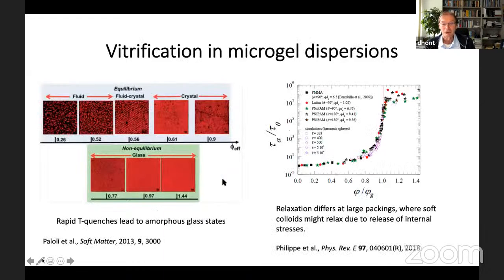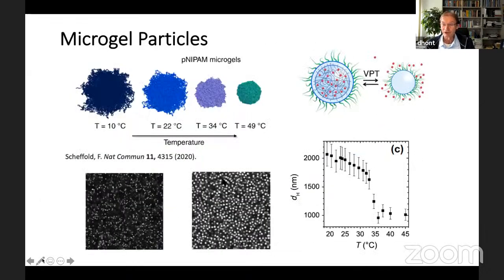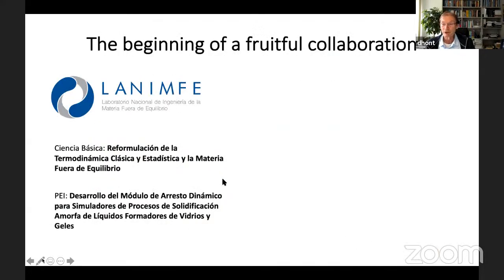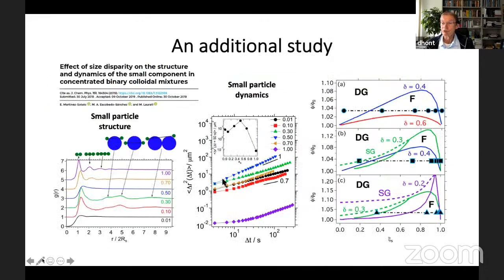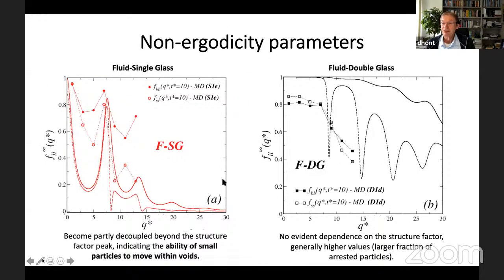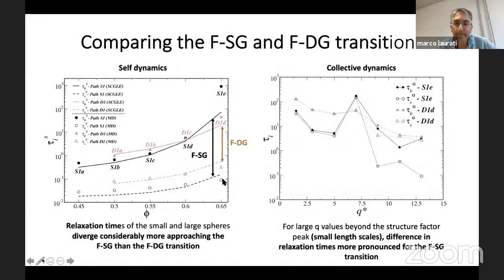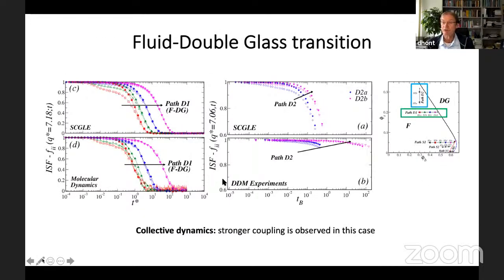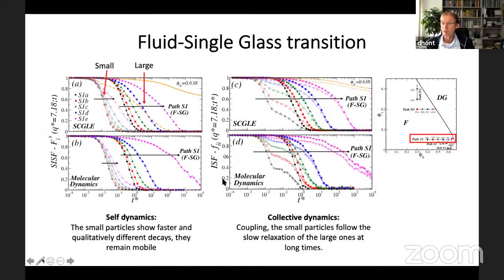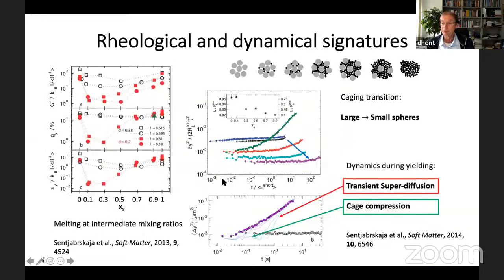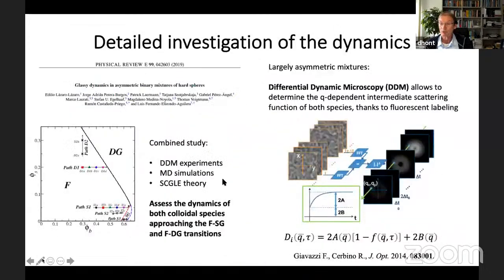But now you find a single glass up to a size ratio of 0.4, where the small ones cannot move through the holes between the big ones. So I don't understand in that case how you can have a single glass. There should be a large fraction of the small ones that should also be arrested at the same time that the big ones are arrested. But nevertheless, you see an intermediate scattering function for the small ones that really drops to 0, which says that all the small ones are still mobile. I don't understand that.